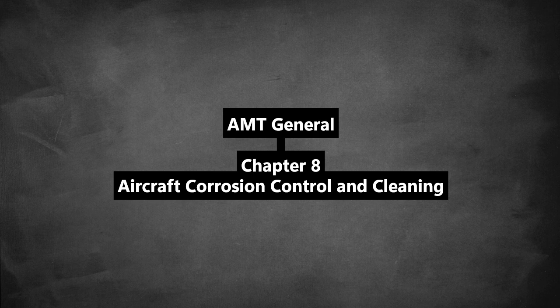Stress corrosion cracking. The combination of stress and a corrosive environment sounds like a recipe for disaster. It's a major concern. The stress can be residual from manufacturing or applied in service, like from fasteners or loads. It doesn't necessarily need super high stress. Failures can happen well below the yield strength. Specific alloy-environment combos are known culprits. Saltwater on high-strength steels or aluminum alloys, for example. Prevention involves coatings, stress relief treatments, inhibitors, controlling the environment, even shot peening to create compressive surface stress.